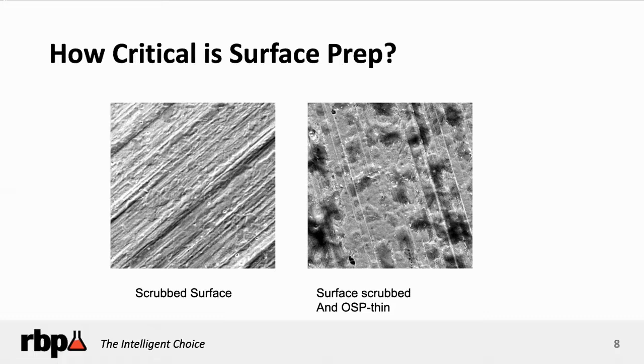And I'm going to call your attention to the picture on the right. You see those dark spots there? There's some nice clear areas which look light. That's where the OSP coated. Those dark areas are areas where the surface was not properly cleaned. There was some oxidation left there. And guess what? The OSP did not form there. And that's going to cause an issue with subsequent assembly, in other words, solderability. So a clean surface prior to applying the OSP is very critical.